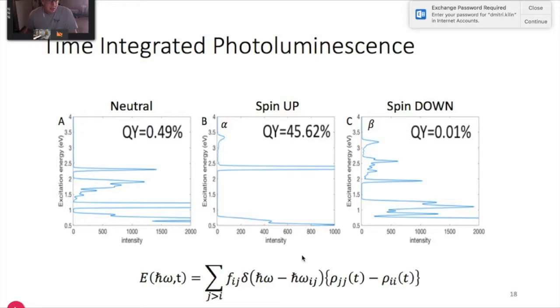And so with the neutral and the spin down having similar density of states or electronic structures, we assume that the quantum yields might be similar, and indeed they're very low quantum yields, whereas the spin up doesn't have any additional defect state put into it, and the quantum yield is close to 45. And so the perfect system isn't on here, and I need to add that when we're done with this. So kind of in conclusion,